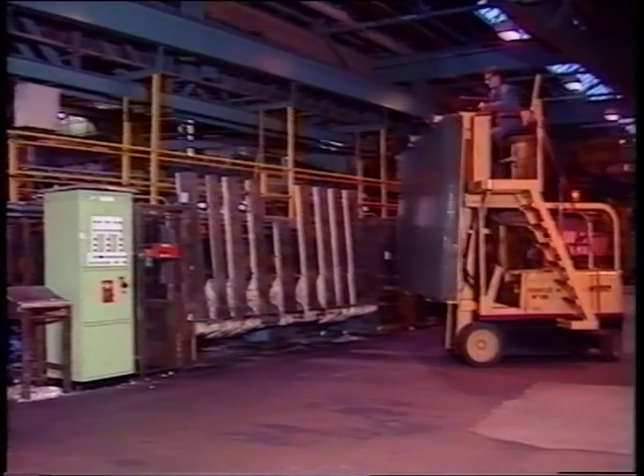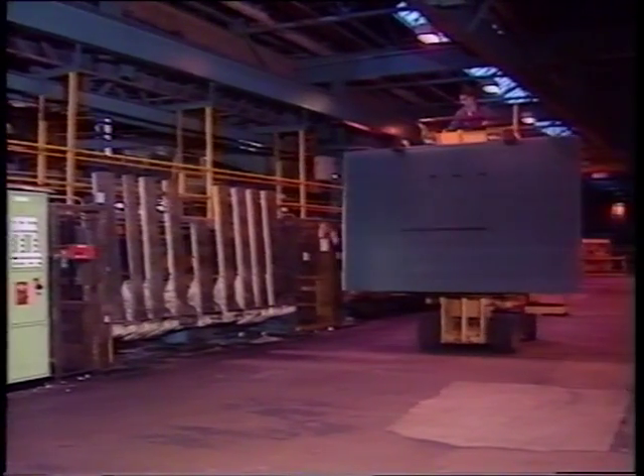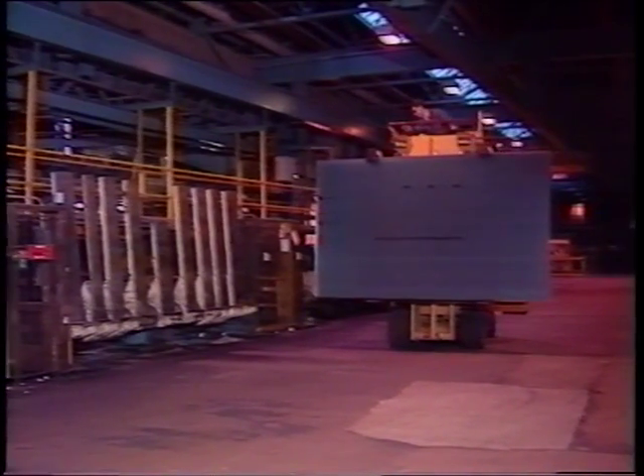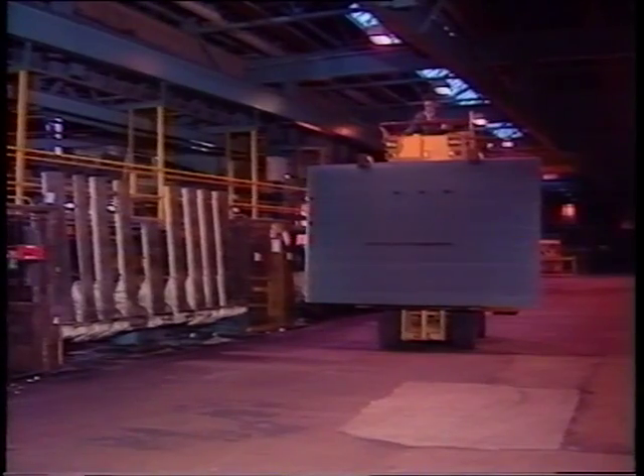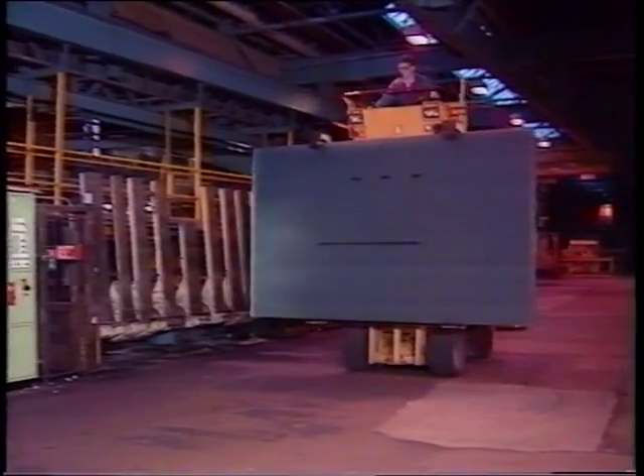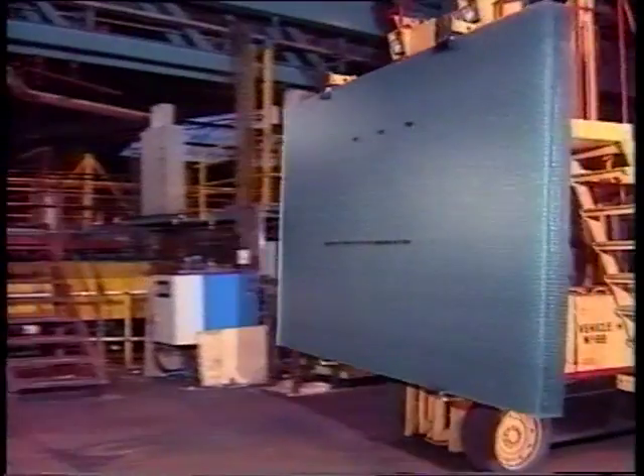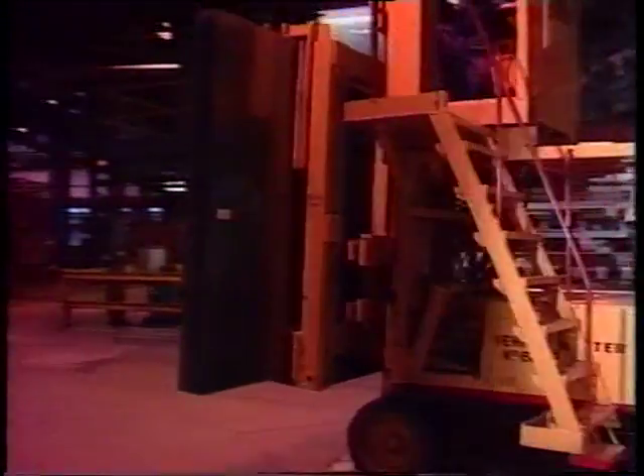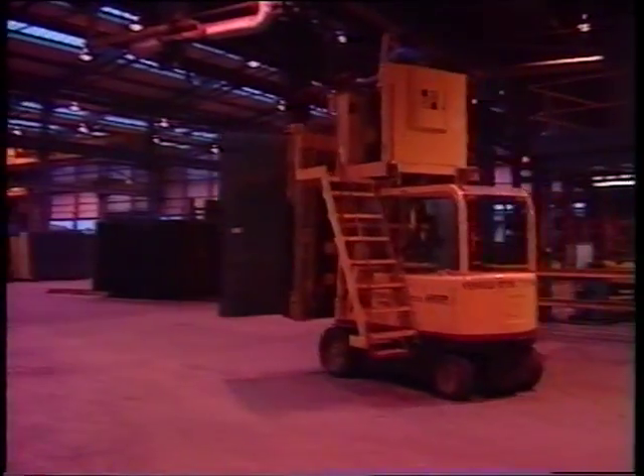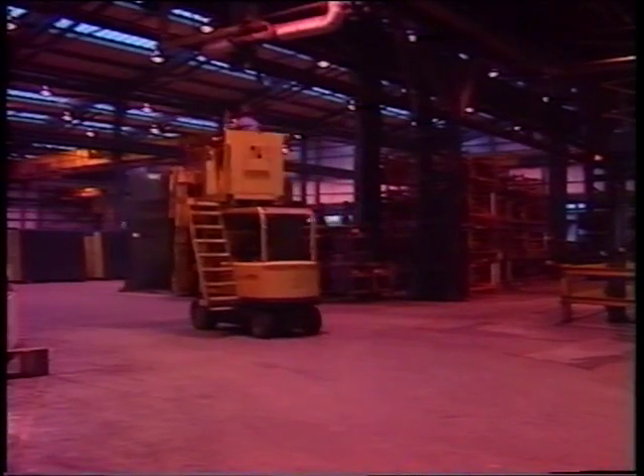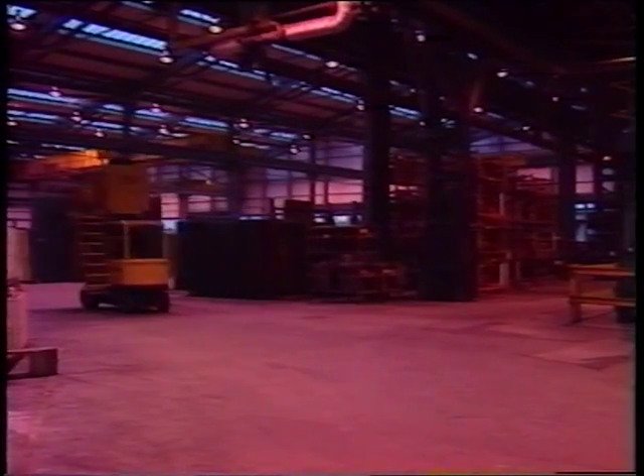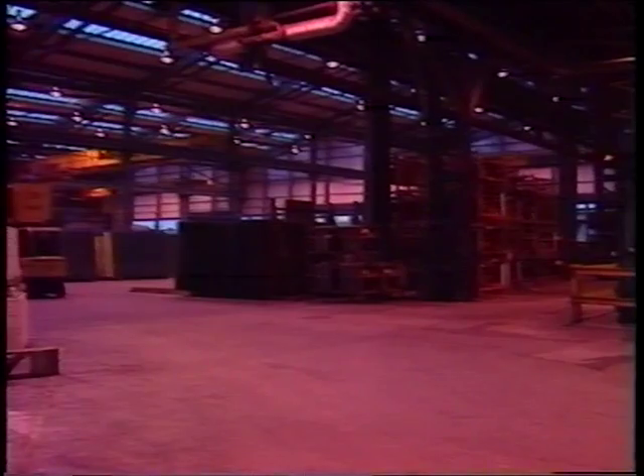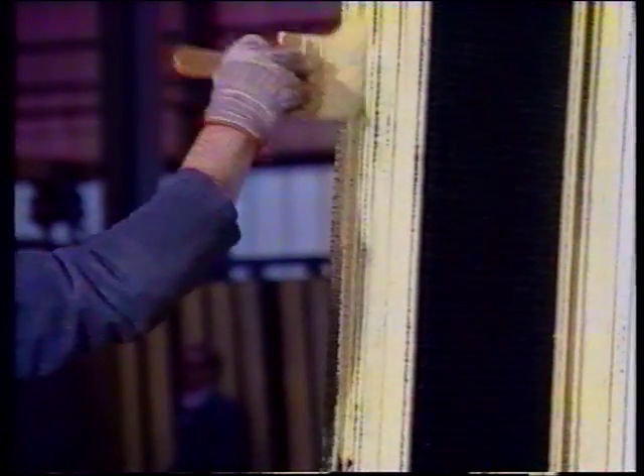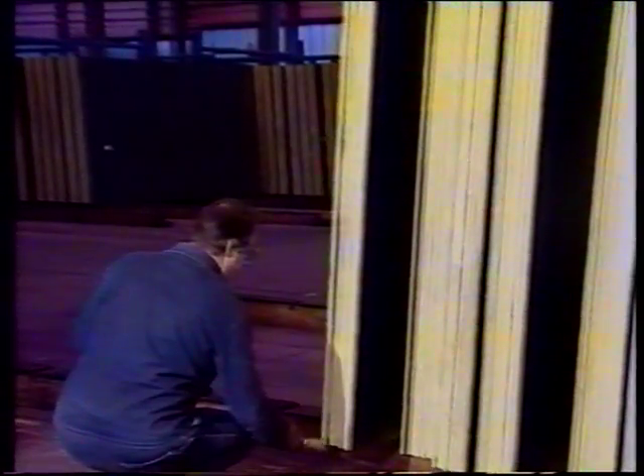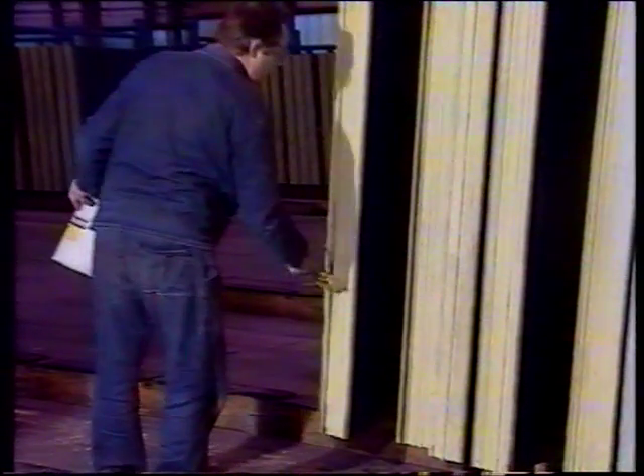This is important, as the glass is still not finally cooled to ambient temperature after the glass-making process has been completed. And if the glass were to be dispatched prior to this 12-hour period, thermal breakages could occur in the packs during transit. The edges of the packs are painted prior to dispatch to prevent water penetrating into the mild steel wire mesh, to prevent rusting.